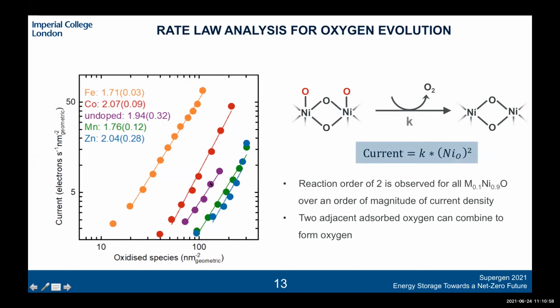And across all these different catalysts, we see that we have an alpha value of about 2. And what this tells us mechanistically is that it's possible that the rate determining step for this reaction involves the chemical coupling of these two oxo species on adjacent nickel sites to form a molecular oxygen. So we've gained a lot of mechanistic insight into how these different catalysts oxidize water into molecular oxygen.